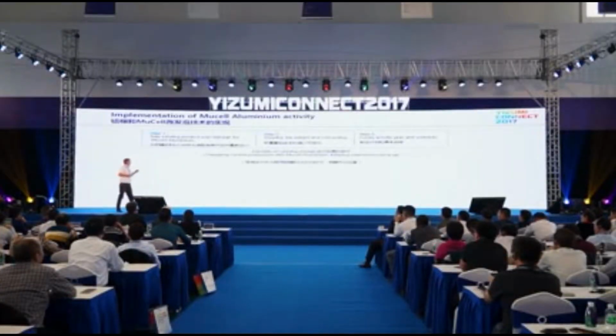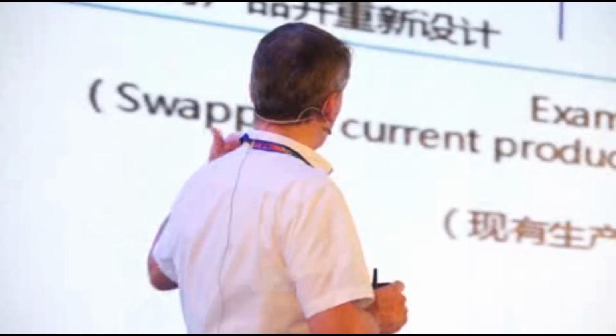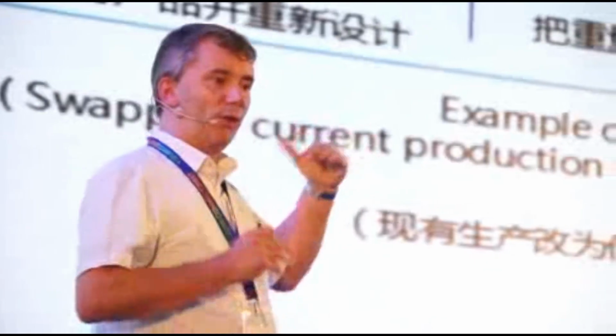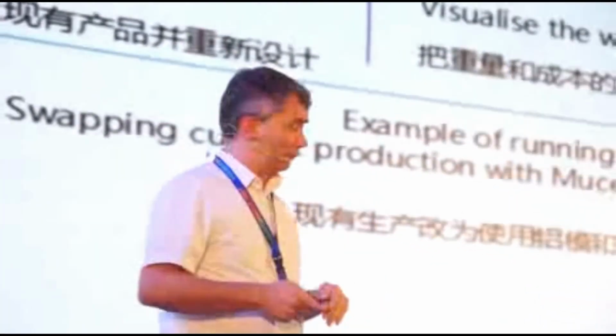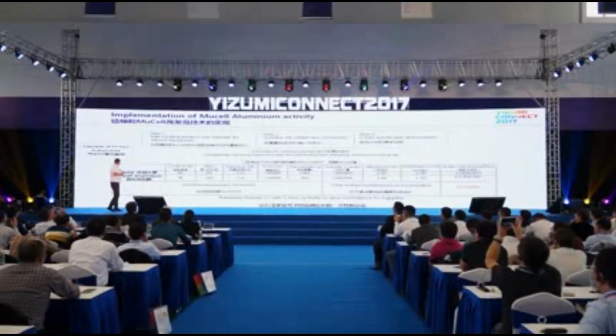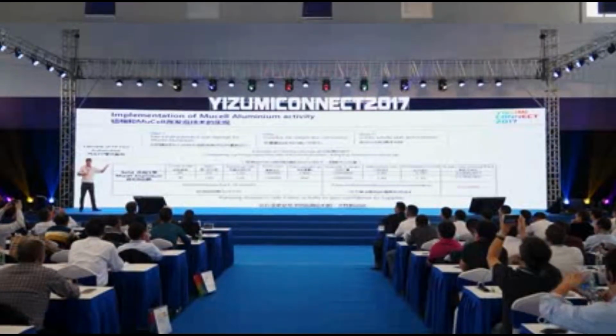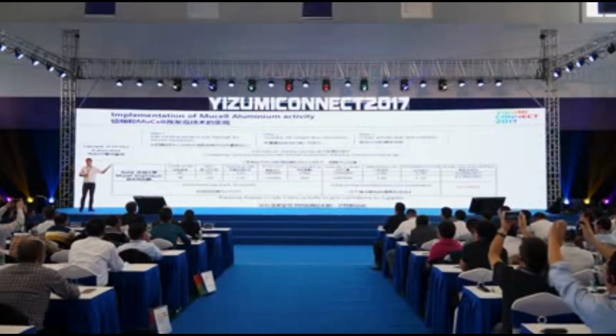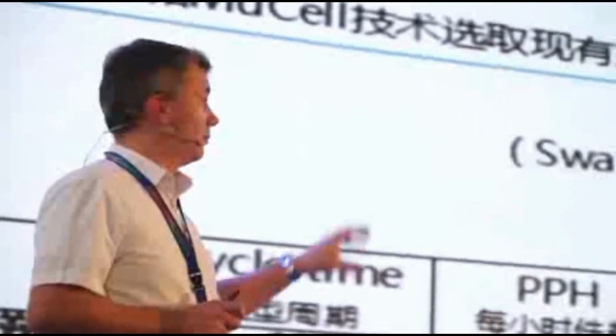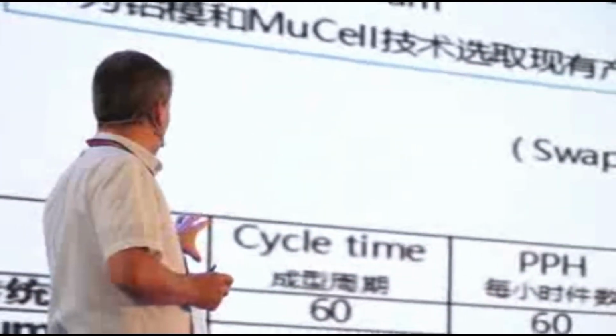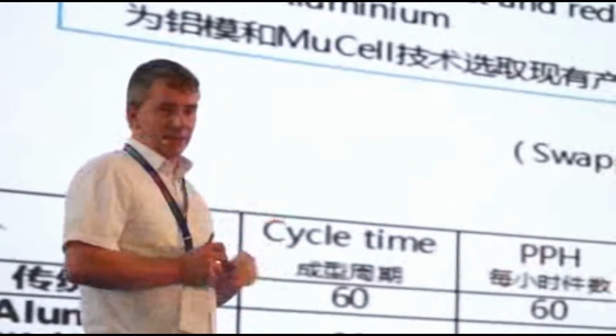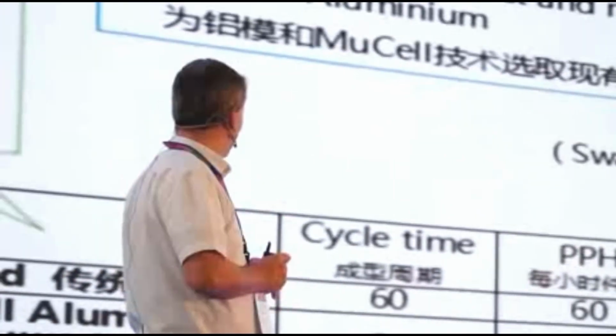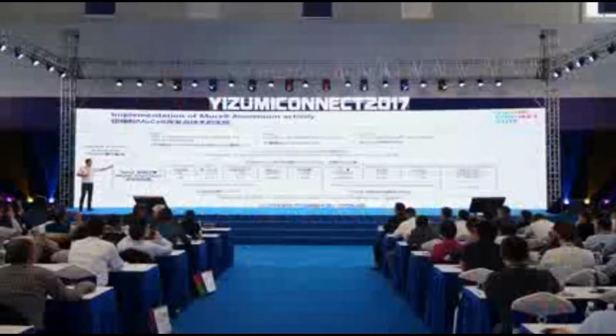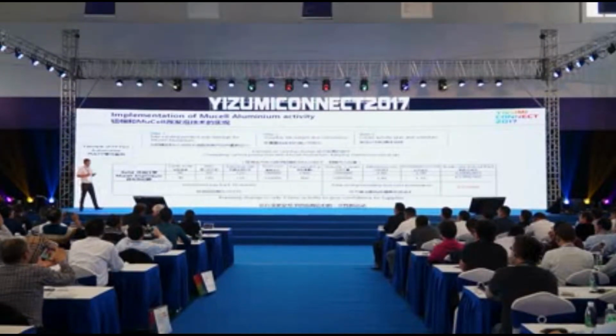So here's an example of what I call a running change, okay? Swapping the current production with a MuCell aluminium replacement. So this is actual results that we had on one product, a polypropylene part for automotive. And if you look at the cycle time, so 60 seconds for the solid part, 30 seconds for the aluminium. So we have, of course, 120 parts an hour instead of 60.